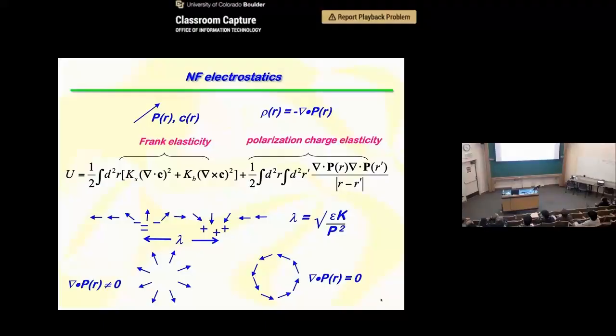All right, so in RM734, if you calculate this lambda, it comes out to something like 10 nanometers, which means that the polarization charge interactions overwhelm the typical Frank elasticity until the director is squeezed down to this very tiny dimension. Okay, so understanding the ferroelectric nematic textures is basically trying to understand how nature is gaming you by finding new ways to escape polarization charge.